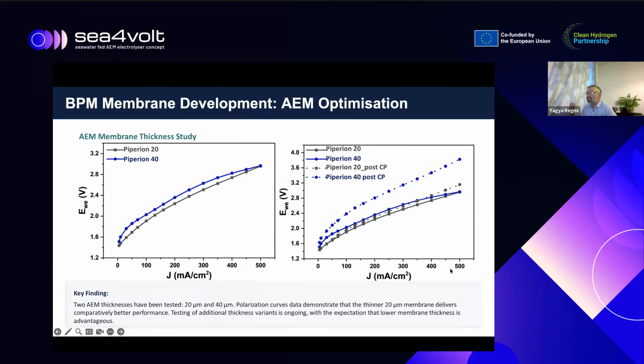So we started looking at different AEMs, different PEMs, catalysts, both cathode, anode, and water dissociation catalysts. Just a quick example, if we change the AEM membrane thickness, Piperion from Versogen, we looked at 4 different thicknesses, but I'm just showing you 2 here. When you use 20 micrometer thick Piperion 20 versus 40 micrometer Piperion 40, you can see that the initial performance, the figure on the left-hand side, is pretty much similar.